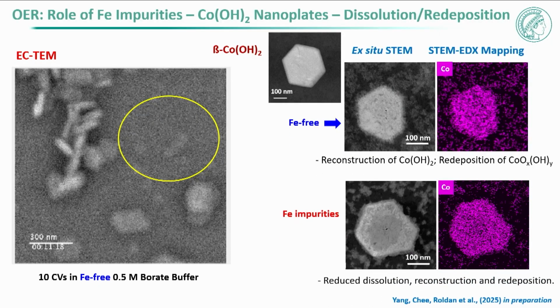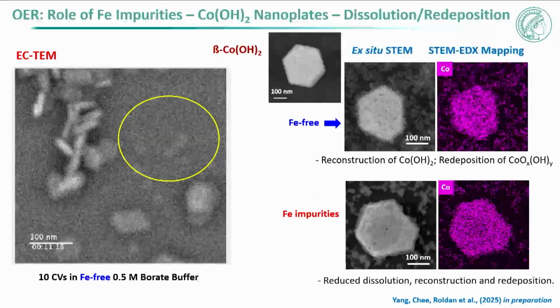And the dissolution of this active catalyst is affected by the presence of impurities. So if you have the iron-free electrolyte, you see more of these particles that are dissolved and redeposit. And if you have the iron impurities, it's more stable. You still see some dissolution, but you see less of the dissolution. Again, a little bit of iron is good. Too much iron starts to create problems.